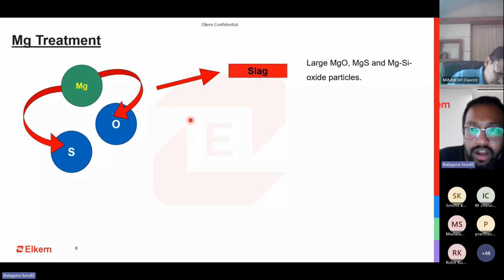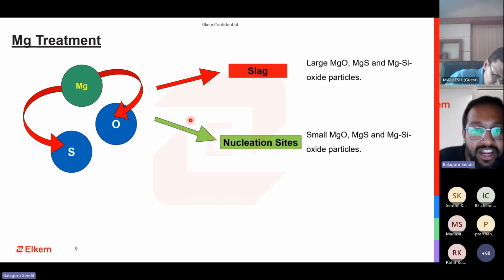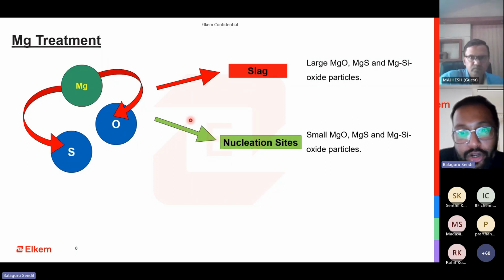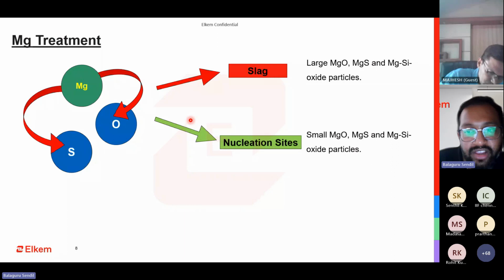And as we discussed in the previous one, we need to form this MgO and MgS. These are the components that are readily formed. But if they are quite big in size, then they become slag and go out. And then we have the creation of nucleating sites. These nucleating sites help the graphite to come and settle there. We have measured these nucleating sites, and they are approximately 1 micron in size. These are very small, so again, the size matters.